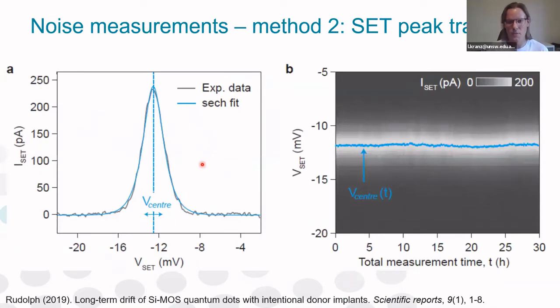Now I'm going to move on to the second method, SET peak tracking, which we use to extract noise at even lower frequencies. So what we do here is we scan over the SET peak over and over again. And what I'm showing on the right is the SET current as a function of measurement time. And this bright line here corresponds to where our SET peak is. For every trace, we perform a fit, and this allows us to map out the position of the peak as a function of time. So we would attribute these fluctuations, again, to some interesting noise in the device that shakes the electrochemical potential of the SET.